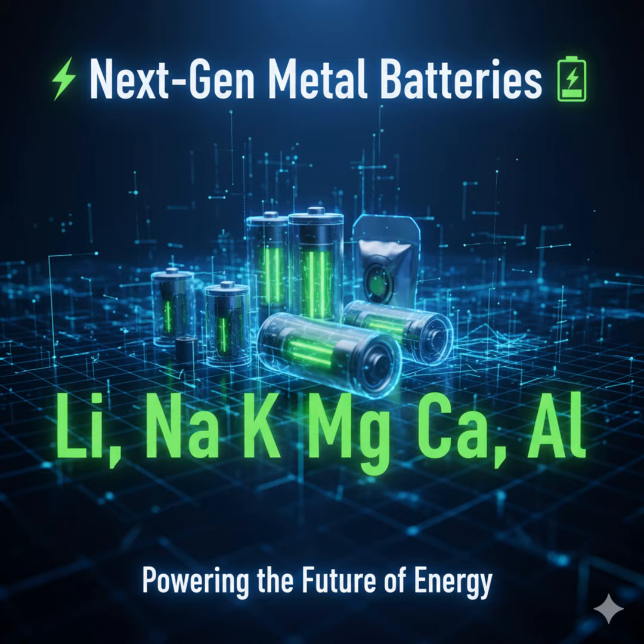You might have this amazing metal with incredible theoretical capacity, but if the ions can't move across the SEI, the battery is dead on arrival. Wow, so it's a complete reversal of the problem. Monovalents have a weak SEI that lets ions through but breaks down. Multivalents form a tough SEI that doesn't break, but it blocks the ions. You've got it. It's this fundamental paradox. Monovalents suffer from an SEI that's too permeable and fragile. Multivalents suffer from an SEI that's too impermeable and robust, at least to ions. Man, batteries are complicated. So how do we fix these totally opposite problems?